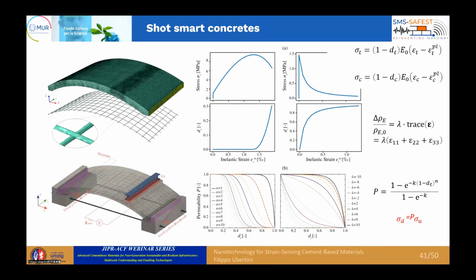So to interpret what we are reading, we realized a multi-physics computational model in Abaqus, where we model the mechanical behavior of the material through the concrete damage plasticity model, so considering damaging in compression and in tension. And we also included, of course, the piezoresistivity of the material, so relative change in resistivity proportional to the trace of the strain tensor, so basically proportional to the volumetric strain. And we reproduced the change in conductivity with the damage through what we call permeability. So the permeability is a factor that multiplies the conductivity, and is a factor that goes from 1 to 0 following these curves that you need to identify based on the properties of the material, as a function of the damage variables in tension and compression. So basically, in this way, we are able to model the material's ability to sense the damage.